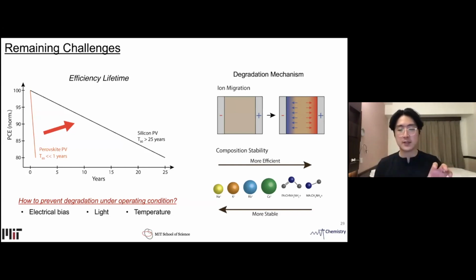If you want to distinguish surface passivation from interface passivation, an experiment you can do is measure the film property with the passivation layer on the bulk perovskite, and also attach a transport layer and measure its property. If you see a significant improvement in performance or film quality, such as photoluminescence efficiency, when we put the passivation layer onto the bulk, it's most likely surface passivation. If we see an improvement in property with the hole transport layer or any transport layer on top, it's most likely interface passivation. So there are ways to distinguish surface passivation and interface passivation. At least from our work, we think a lot of the benefit is coming from interface passivation.